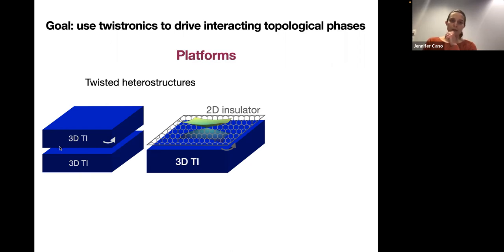So at the interface between them, we'd have these two different Dirac cones, and maybe these things would behave similarly to the two Dirac cones in twisted bilayer graphene. We thought about this approach, and I'll explain it at the end if there's time. The bottom line is that we can get magic angle conditions, but there are a few caveats. In addition, I'm not sure about the feasibility of this heterostructure because these TIs are really 3D, not 2D materials. So I then turned my attention to what I think might be a more reasonable heterostructure.